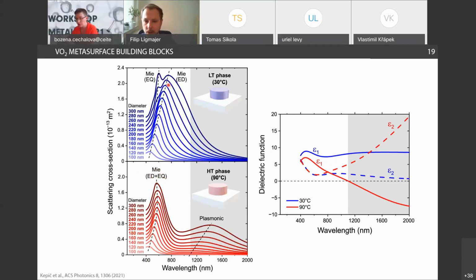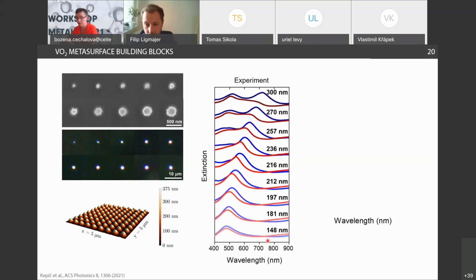And at room temperature, you still have a positive dielectric constant, and you have these two modes now a little bit more separated, and at least for large disks, you can see both of these modes separated. And of course, this was a simulation based on just this dielectric function, but Peter spent a lot of time optimizing the depositions and nanostructuring of this material, and he was able to achieve quite nice arrays of VO2 nanodisks or nanocones, as you can see from this AFM image,